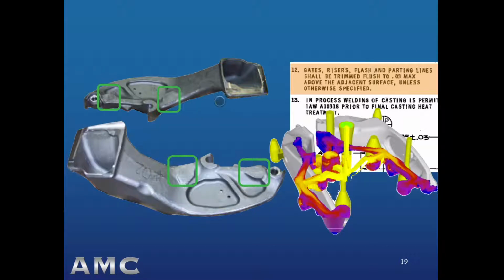This is on a steel casting, and this is that same kind of process interface geometry that we saw in the video, attached to the casting, delivering the liquid steel into the mold cavity and helping it set up with solidification gradients that meet the mechanical properties in the microstructure. And these are what these cut-off surfaces actually look like. You can see they're a little higher than the adjoining mold walls. There's a little bit of surface roughness because it's hand ground and then media blasted to look as close to the as-cast surface as possible.